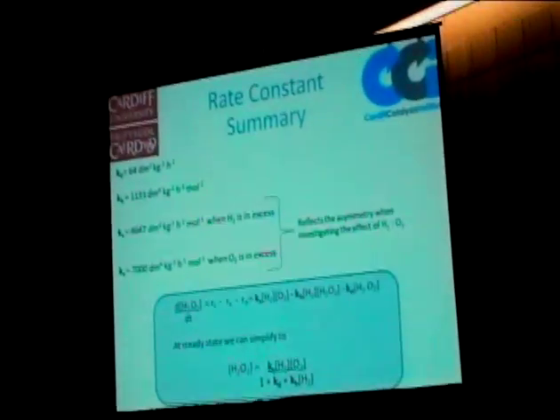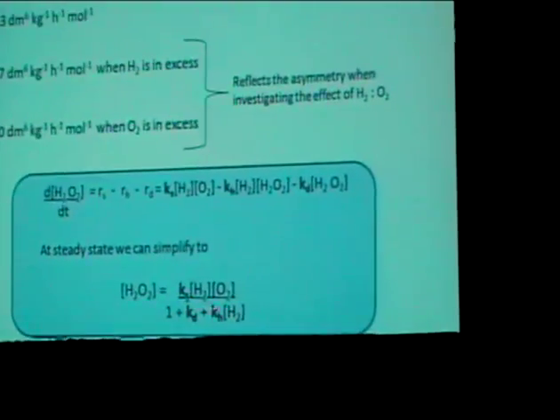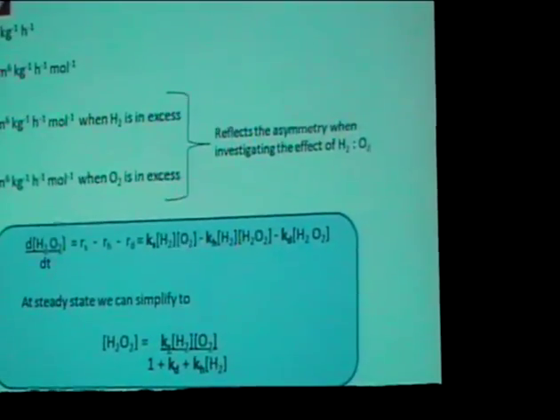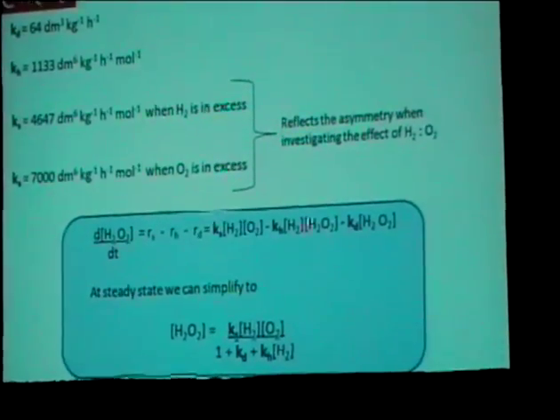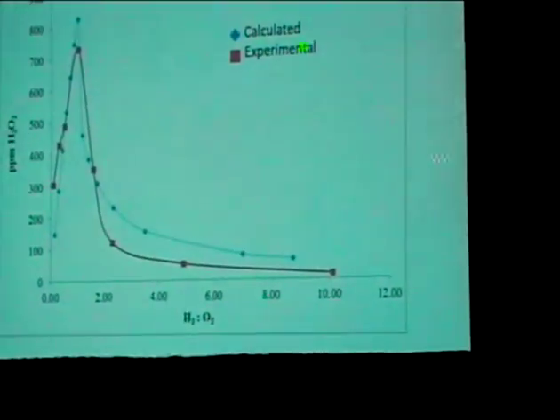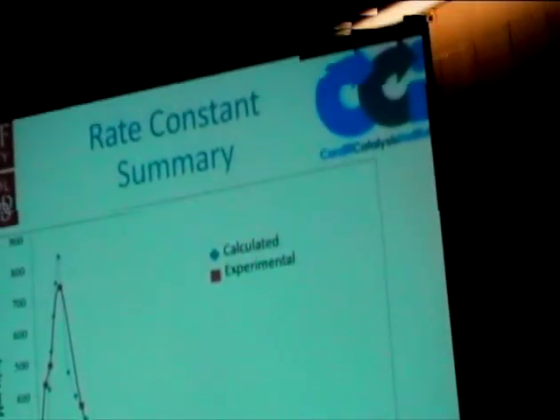We then put our rate constants together. We plug our rate constants into this equation, and the concentrations of the hydrogen and the oxygen that we use during the synthesis. And we can see that our calculated concentrations of hydrogen peroxide fit very nicely with the experimental.